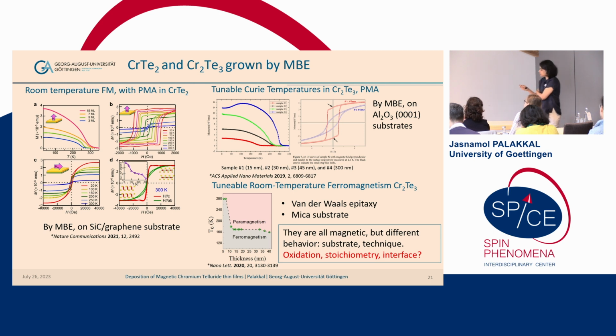And there are quite a lot of reports coming recently on this material, as you can expect, because room temperature magnetism is highly important, and if this is a 2D material, then you can use it for a lot of applications. But here, in these three reports, they reported the magnetic moment in emu. They are not even reporting, so here I didn't include that MH curve or MT curve, but these reports are reporting the magnetic moment in emu units, or they are not reporting it in absolute units.